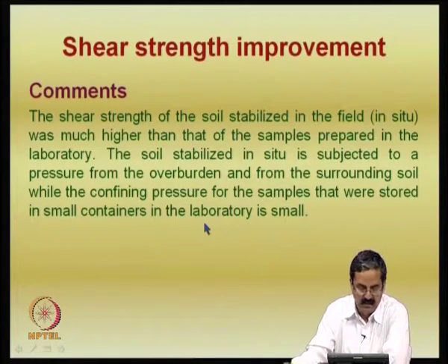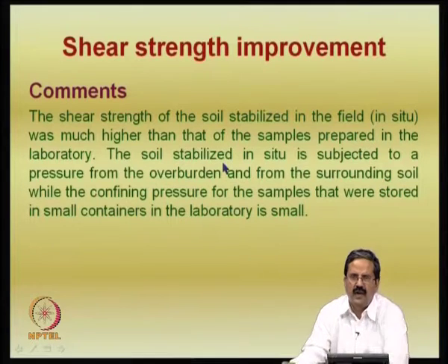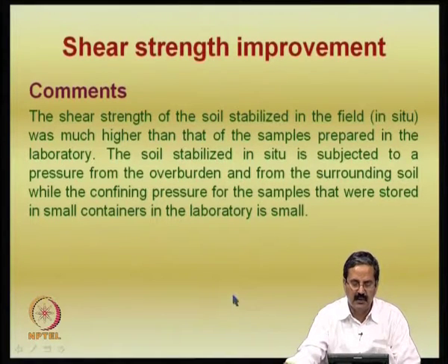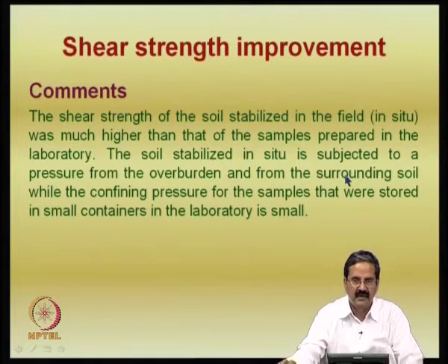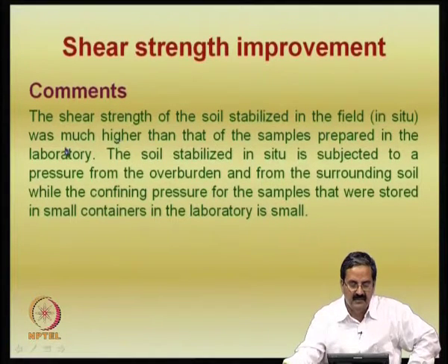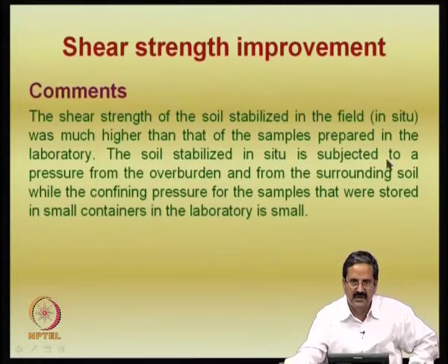Okay. So, actually what you get from the lab is just for a simple mixing, and then in a simple testing people normally do, they make some inferences that it is very effective. But what happens in the field is that the area that you are trying to handle is very big, and the strength of the soil stabilized in the field is much higher than that of samples prepared in the laboratory. The soil stabilized in situ is subjected to a pressure from the overburden and from the surrounding soil, whereas the confining pressure for the samples that were stored in the small containers is small.